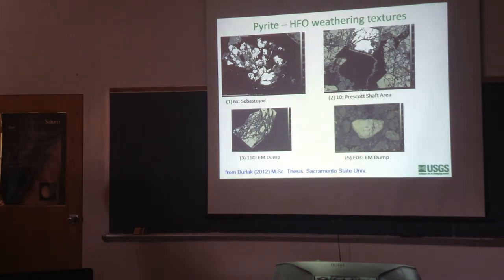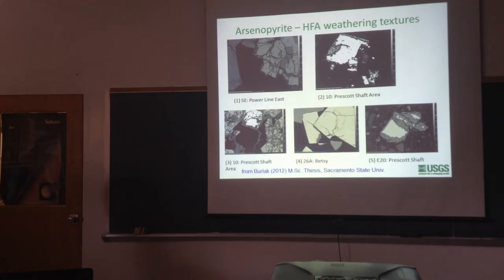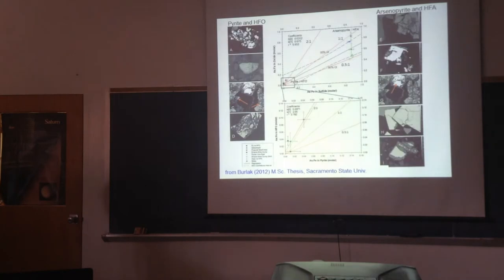And so some of the textures that Tamsin documented were a replacement texture of oxides coming in along microfractures inside the pyrite veins, replacing it from the inside out. And again, you see a lot of this microfracturing that controls the distribution of the secondary minerals. And that was on pyrite. You can see a similar thing on arsenopyrite. We see a lot of microfractures that control it. And we see rimming as well, the secondary minerals rimming the primary minerals, and a relic grain of it, in this case arsenopyrite, in the middle here.